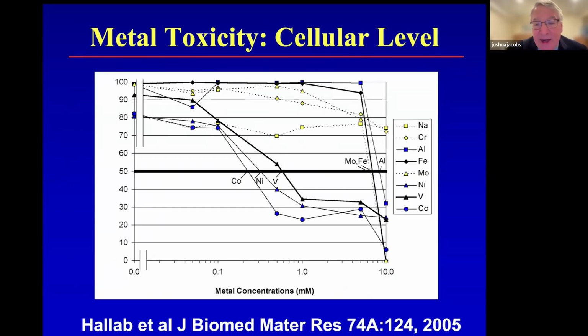And at higher concentrations, these metal ions can actually kill the cells. This is a study looking at cell toxicity, at somewhere between 0.1 and 1 millimolar, and you can get concentrations as high with a failed cobalt alloy prosthesis. Cobalt in particular can lead to cell death. And why am I presenting inflammation and cell death in these cell studies? Because that's what you see histologically, and I will show you a slide of that shortly.